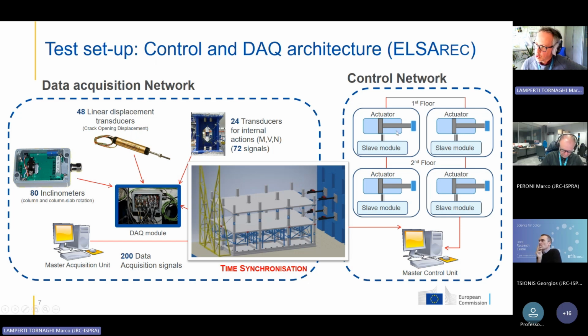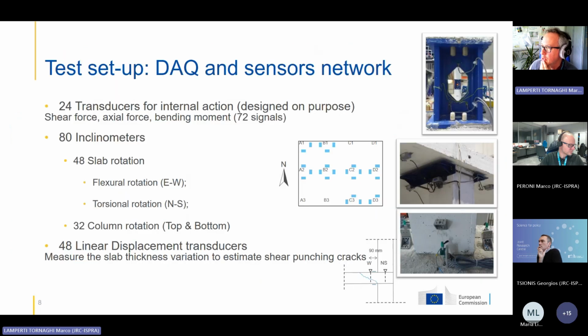That gives also the displacement of the actuator during the test and the load measured by the load cell mounted directly on the actuator. This allows us also to check the goodness of the measuring of the shear load by the internal instruments, because the difference between the load measured by the external actuator and the internal transducer was only 4% of error between the two measures.